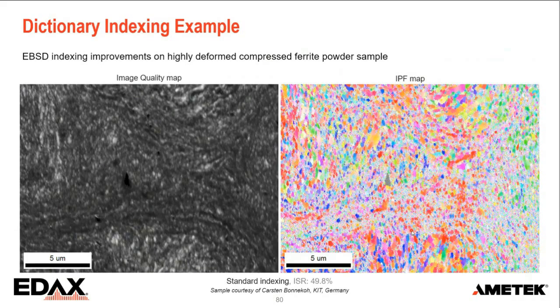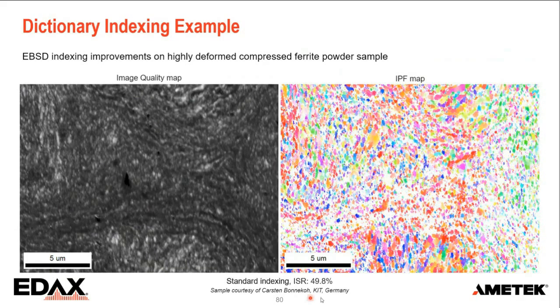And when I then apply a CI filter, we still have about 50% indexing success rate, but there's a lot of area where we cannot get an indexing result. Now, we could try NPAR to improve the patterns, but on a material like this, there's a very big risk that the neighbor pattern is from a different orientation, from a different grain. And in many cases, that will actually degrade the indexing success rate. So that's not really an option for this material.